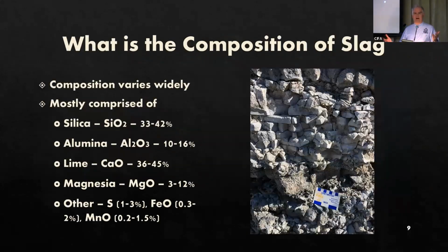Well, with all that discussion about slag, what is it made of? Because of how the slag forms in the furnace, slag has a wide range of properties and compositions. The composition of the slag will vary as a function of what materials are added into the furnace, the limestone or the flux, the iron ore, the fuel, the proportions of those materials, the quality of iron that's produced in the furnace, and how the furnace is operated. So that composition, you might well imagine, will vary a lot. Slag compositions, in fact, can vary from cast to cast using the same solid materials being added to the furnace. And sometimes even within a single cast, the slag composition can vary in the same furnace.